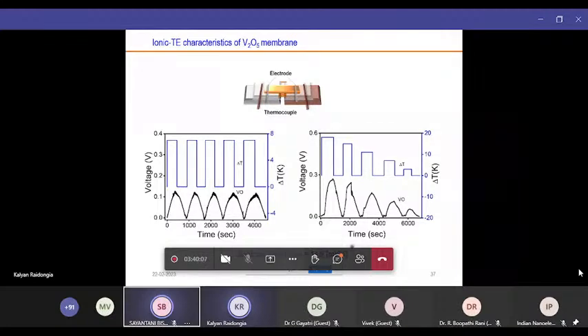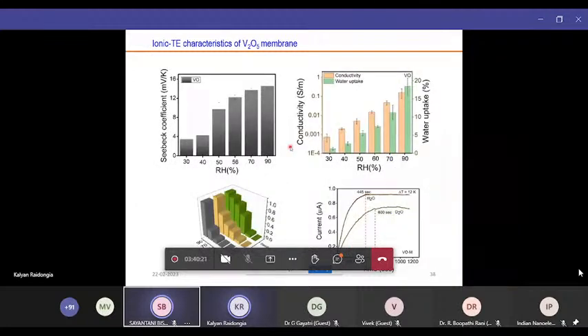This is not the best, but this is the first example of ionic thermoelectric materials of a layered material. This is still a very inspiring number. Similarly, we can also do lots of experiments to find out the actual mechanism of this thermal transport. By varying the humidity, varying the conductivity, and all these things, we can see that the temperature gradient induced proton transport is the reason behind this observed thermoelectric potential.